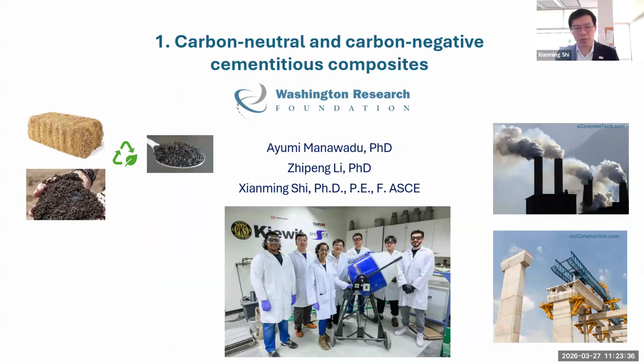So today, in terms of the beneficial use of biochar in concrete or cementitious composites, I share with you 4 different studies. Actually, some of this is not yet in the published domain. The first one is sponsored by Washington Research Foundation, and my team was here when I was a professor at Washington State University a couple of years ago. Ayumi and Zhipeng are the main doers for this project, and you can see we look into 2 types of feedstocks, wheat straw and a biosolid. I believe it's cow manure. Through a process known as pyrolysis, you basically heat it up to really high temperature, typically 500 to 800 degrees Celsius, with very little oxygen, and then you generate biochar.